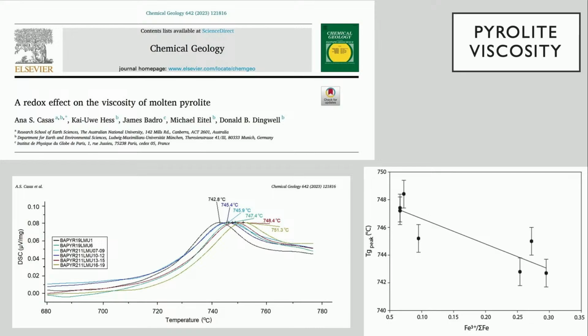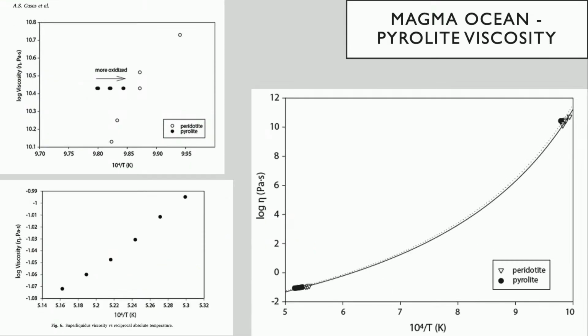So we hyperquench these liquids in the laboratory, we melt them by levitation, and then we quench them. They have containerless freezing, so they're avoiding nucleation. And then we look at their iron oxidation state, and we look at the glass transition as a function of iron oxidation state. And these are the actual raw data which allow you to do this.